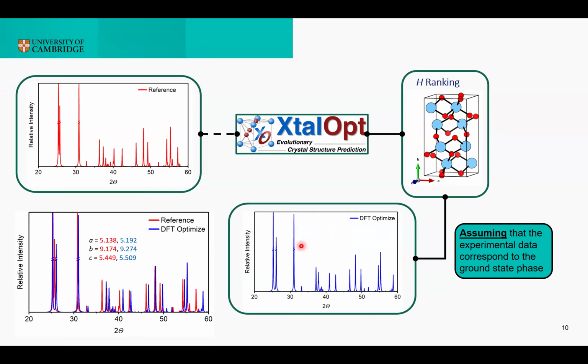Moreover, and most importantly, we know that the structure we calculate cannot perfectly match the experimental data, such as experimental powder diffraction, due to the various approximations that we use, not only the DFT functionals, but the fact that we are doing a calculation at 0 Kelvin and so on. And this is particularly true when we try to compare our calculation with data collected maybe at a high temperature or high pressure, since even small differences in the unit cell can have quite a big impact on the powder diffraction pattern, making this theory to experiment comparison not always so straightforward.